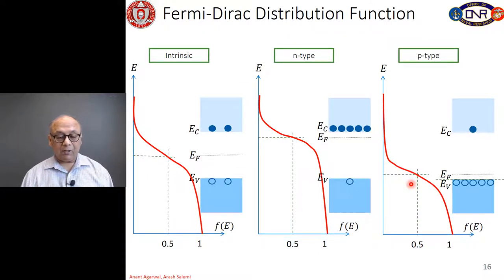All right, so now we can apply this concept to the intrinsic material on the left-hand side. So, here we have a conduction band, valence band, and the Fermi level for the intrinsic material is in the middle of the band gap. And we have plotted the Fermi function with the red line showing that probability of electron occupation of a state is very low above the Fermi level. But we know there are intrinsic number of electrons in the conduction band, intrinsic number of holes in the valence band if the material is intrinsic, and therefore we have small number of holes in the valence band, small number of electrons in the conduction band, and Fermi level is exactly in the middle of the band gap.